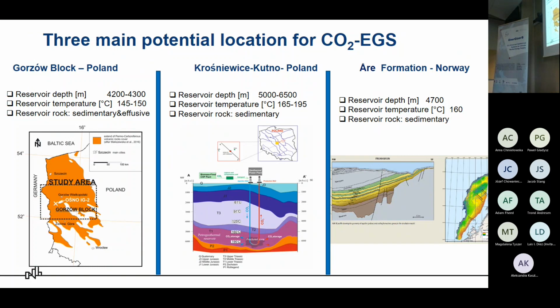There are also sandstones, but these are sandstones of the lower Triassic reservoir. And because of the deeper reservoir, the temperature is also higher. It's between 165 and 195 Celsius degrees. And other geological conditions are connected with the other formation, this offshore formation selected by our Norwegian partner. The reservoir temperature is near 160 Celsius degrees. And there is also sedimentary rock, mostly sandstone.